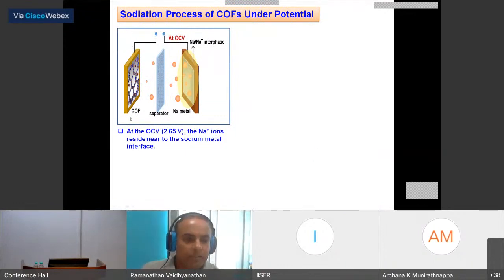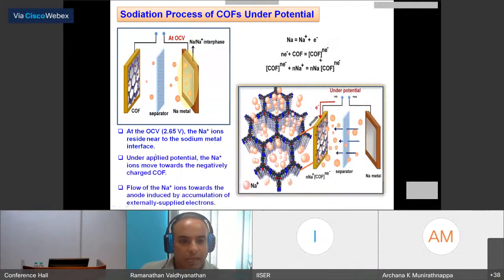You can see, if I make the COF with this lowest HOMO-LUMO gap containing material, at the open circuit potential, all the sodium ions will remain at the interface of the electrode and the electrolyte, but they will not move into the electrode. Once I apply a potential, what will happen? All the sodium ions will rush into this negatively charged